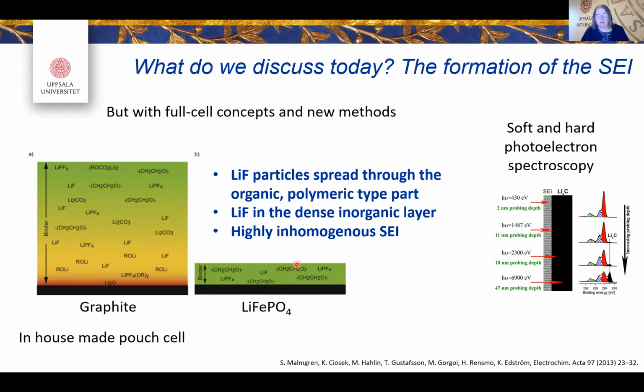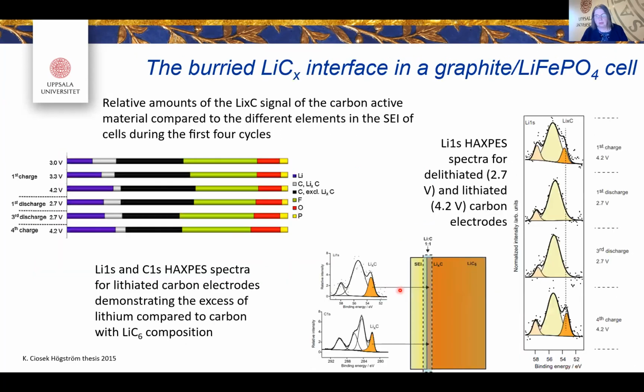The lithium fluoride is very different. It's this much thinner, as I indicated before, and the layer is more like the composition we have in the outermost SEI here on the graphite. And in fact, we can also find a little bit of iron on the graphite surface by dissolution from the lithium iron phosphate. This is also well known, and it's related to interface reactions, where you have LiPF6 giving you some HF, and therefore also some kind of etching of the lithium iron phosphate.